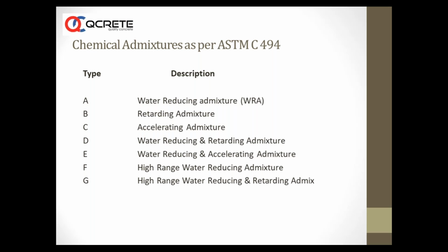The beauty of these supers, classified as class F and class G, is that the water reduction capability has increased manifold from 5 to 12% for plasticizers, which is WRAs, to 20 to 25% or 30% in case of high range water reducing admixtures.